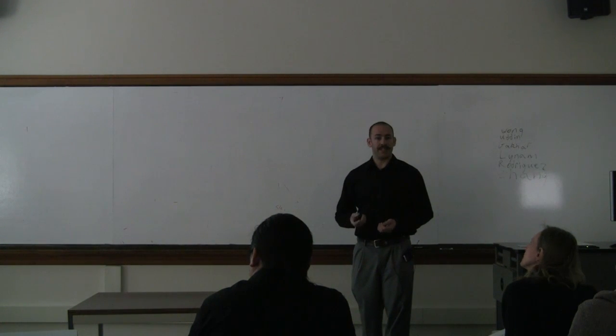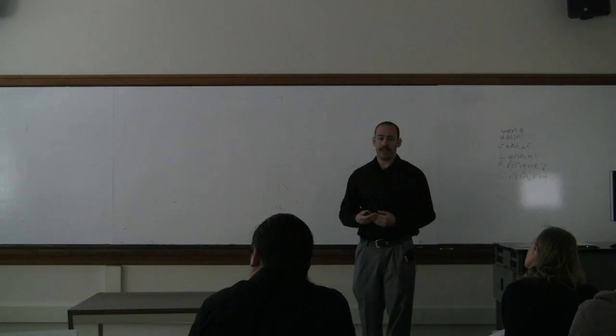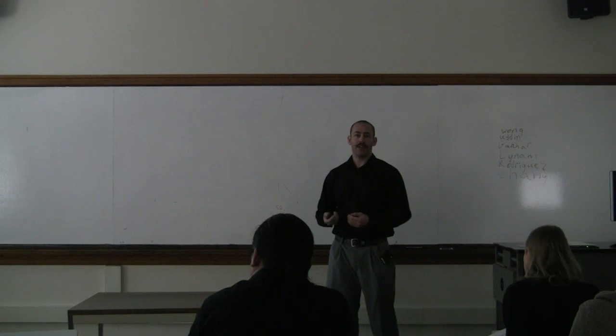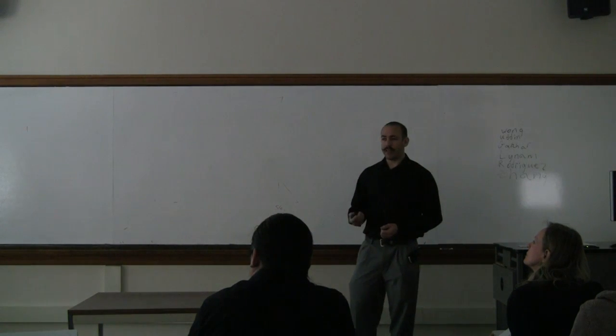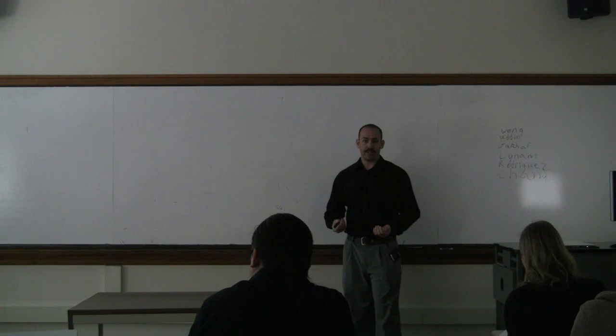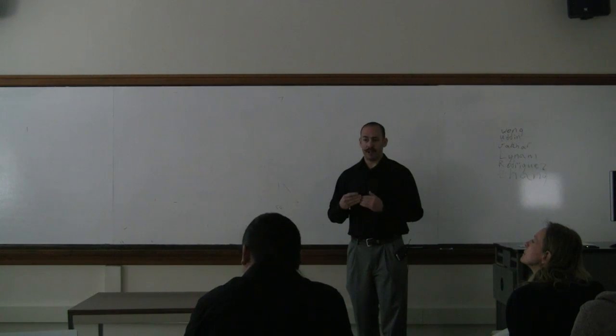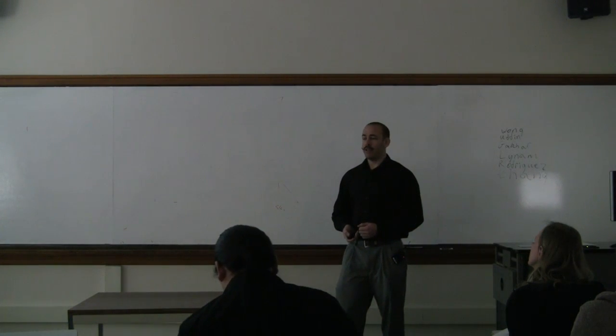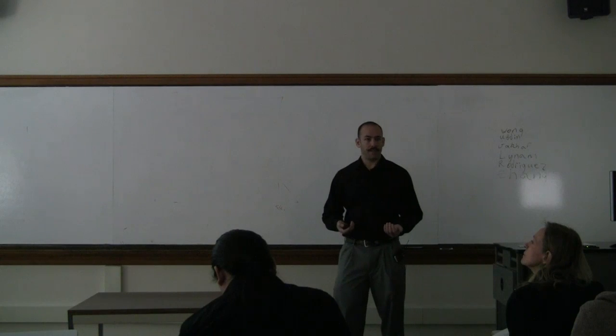Aluminum alloys are very important to the aerospace industry because they have a high strength to weight ratio. So they're low density compared to steel, but with alloying elements, they can be comparable with the strength of steel. But with the added alloying elements, we get an increased rate of corrosion with aluminum alloys because we do not have the aluminum oxide layer rapidly forming on the surface of the alloy. So we need to coat this with something to prevent it from corroding on the airplane.